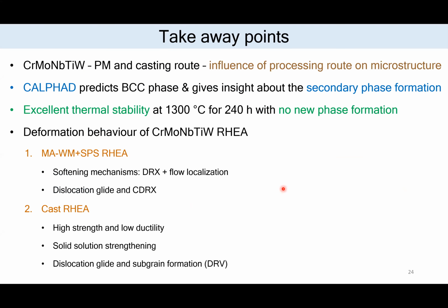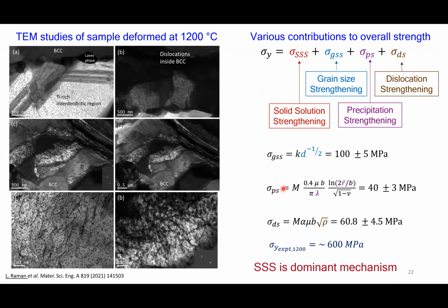Hello, can you hear me? Yeah, it's a very nice presentation. I have one question towards the last slide, the strengthening contribution that you shared. Did you calculate the dislocation density to find the dislocation strengthening contribution? Yes. Did you do that from the TEM, or from EBSD, or some XRD experiment? No, from the TEM. These are the two images which I have shown, but I had to take multiple images with more dislocations. You can calculate the dislocation length in a given area and calculate the dislocation density. So you had to take into account the foil thickness of the TEM? Yeah, lamella thickness. Okay.